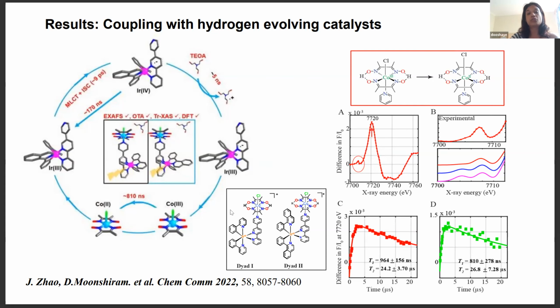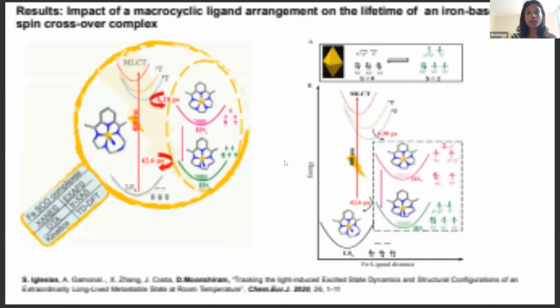And through combined experiments and DFT calculations, we were able to find that the reason is because the lowest triplet state for one of the photosensitizers was the MLLCT transition, the mixed metal-to-ligand charge transfer state, whereas the other one was a combination of CN-centered MLCT and ligand-centered transition, which helps to decrease the efficiency of the MLLCT transition and helps it decay back to the ground state faster.